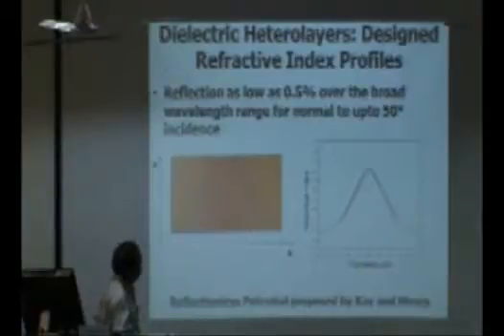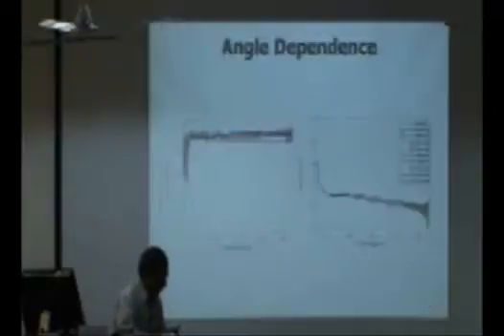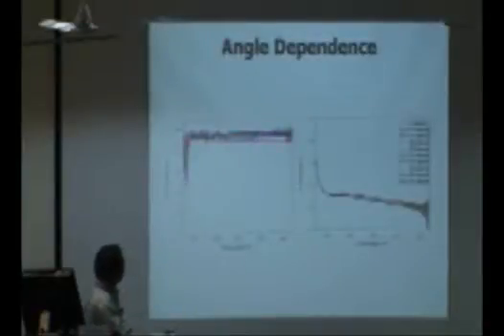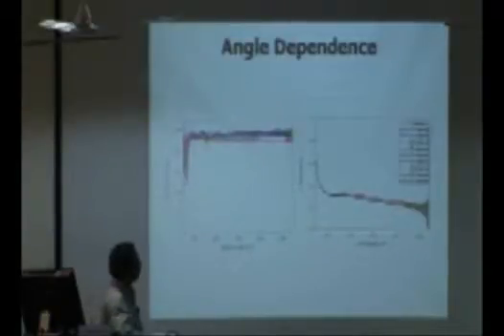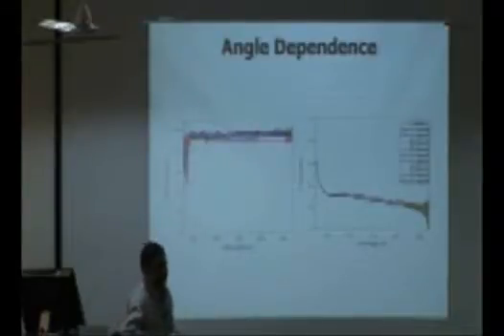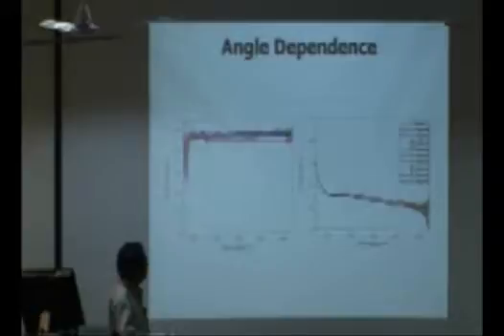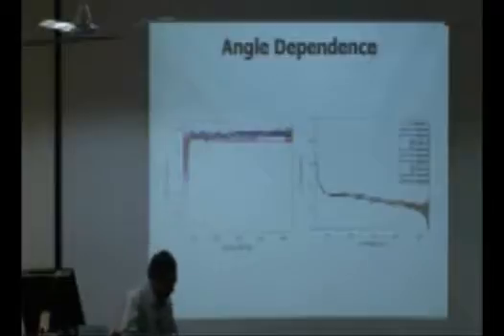This was proposed by Kay and Moses long ago, and Dattagupta and Agarwal have shown that it can be used for anti-reflection potentials at optical wavelengths. So we have designed and fabricated these heterolayer structures which conform to reflectionless potential, and showed that we have very small, less than 1% reflection over a broad 500 to 2500 nanometer wavelength range, and for normal incidence up to 50 degrees, which we could measure. So it's very low reflection and very high transmission in these layers.